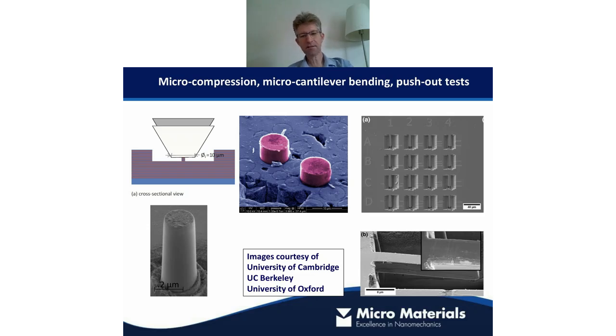So Andy alluded right at the end of his talk to the fact that, as well as an indentation test, there are lots of other things that you can do to take advantage of the very precise control on the load that you apply, the displacements that you measure, and the position accuracy at which you do the test. Some of these are shown here in examples from the universities of Cambridge, Berkeley and Oxford. And what they've done here, for example, is use a focused ion beam to mill out a pillar of a material of interest, and then they've squashed that pillar with a flat punch. And again, this is another way to get yield stress information from the test.